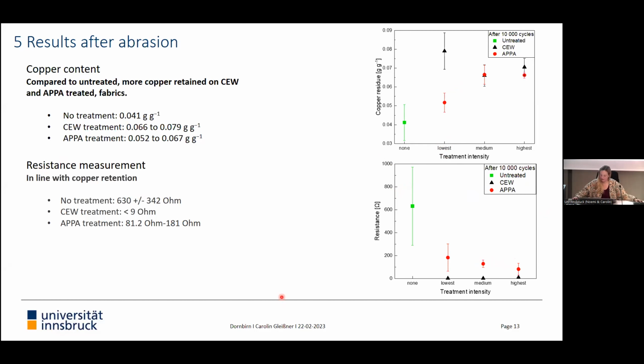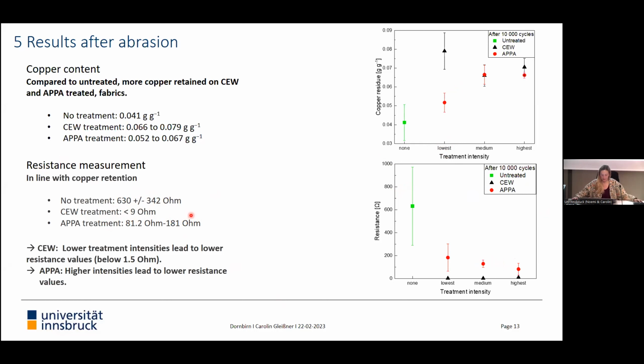The non-treated fabrics show a resistance around 630 ohm with a high standard deviation. The plasma treated fabrics are between 80 and 180 ohm, and the CEW treated fabrics show quite a small resistance below 9 ohm. Lower treatment intensities for the CEW treatment lead to lower resistance values, and higher treatment intensities for the plasma treatment also lead to lower resistance values.